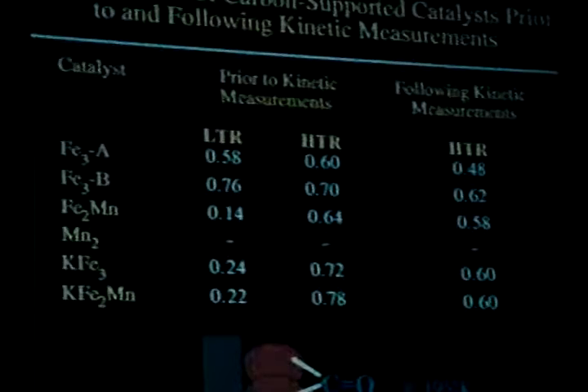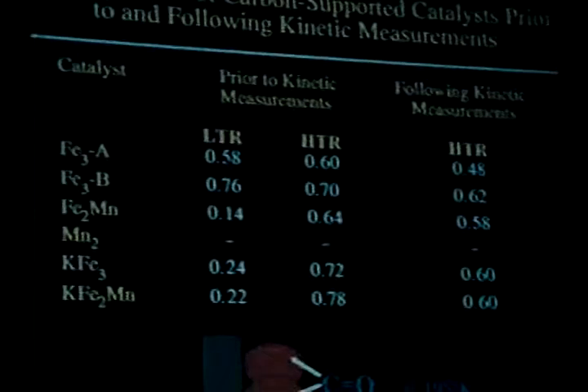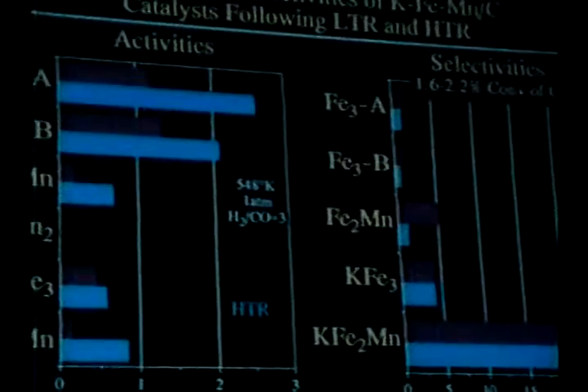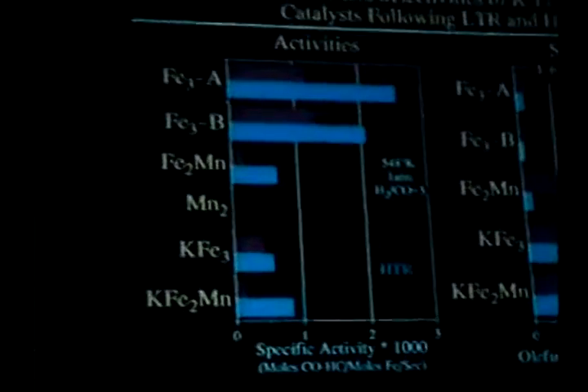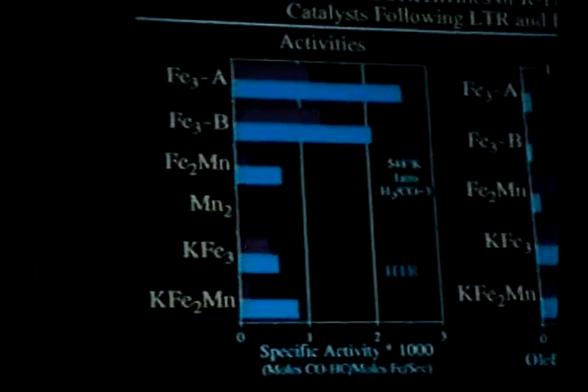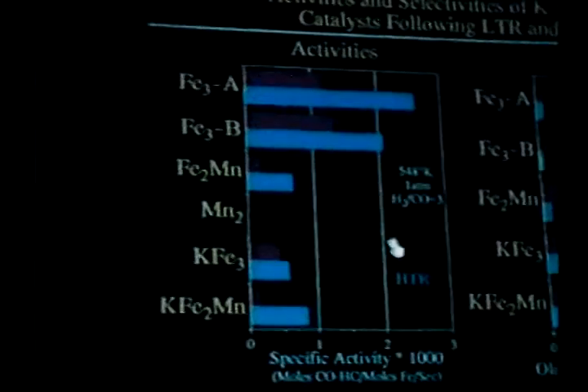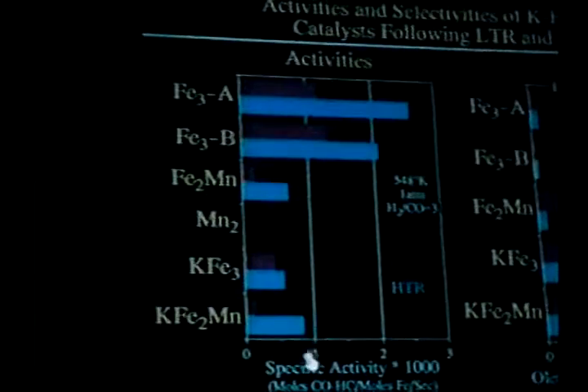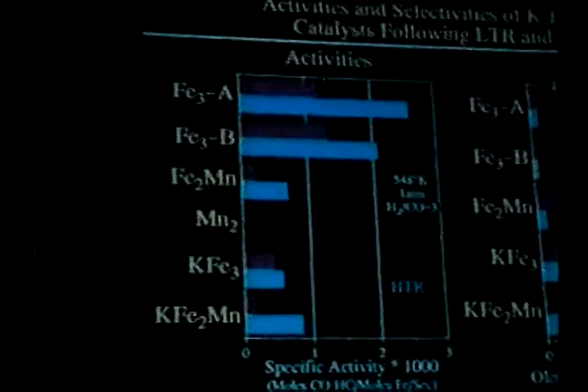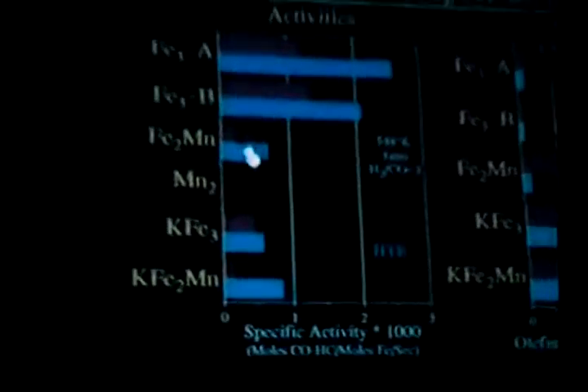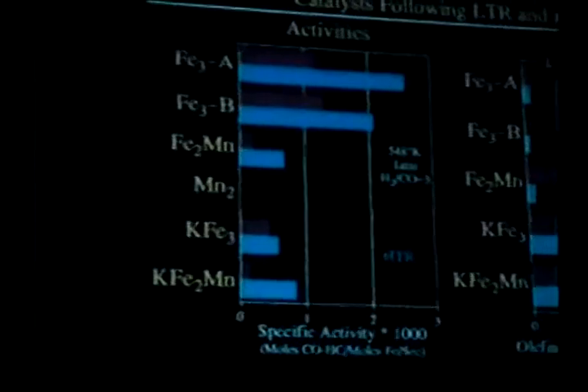The Fe2Mn cluster has the interesting property that dispersion increases significantly following the high temperature reduction, due to the catalyst becoming somewhat more iron-like in its kinetic properties. The kinetic and selectivity results show that activities after low temperature reduction were about one unit. For all catalysts, activities increased following high temperature reduction, approaching but remaining lower than those for pure iron.